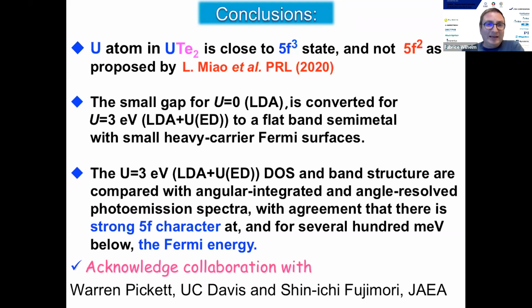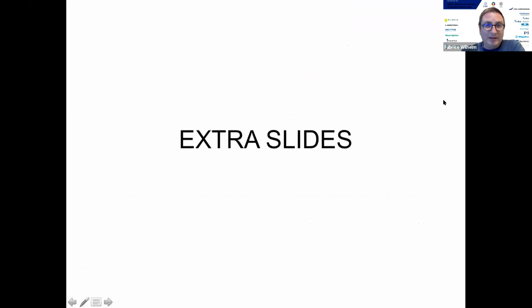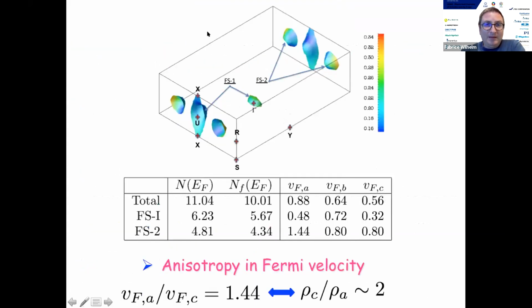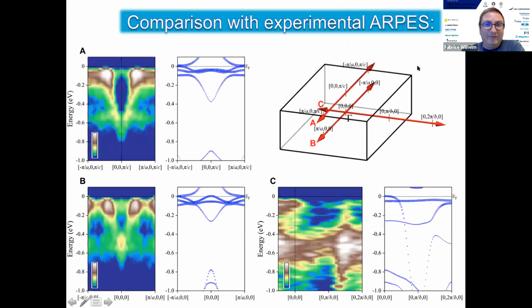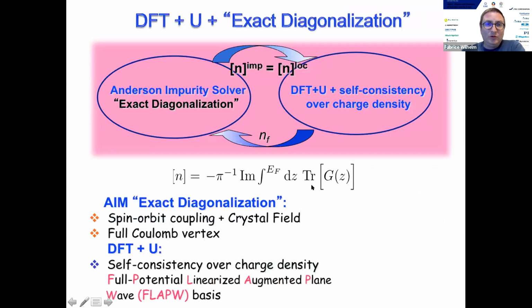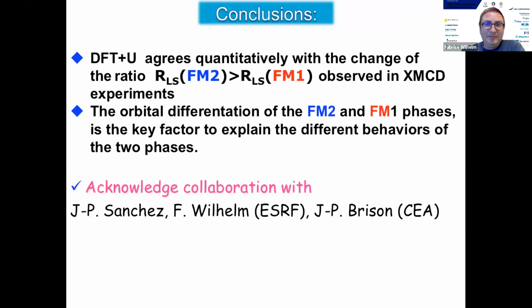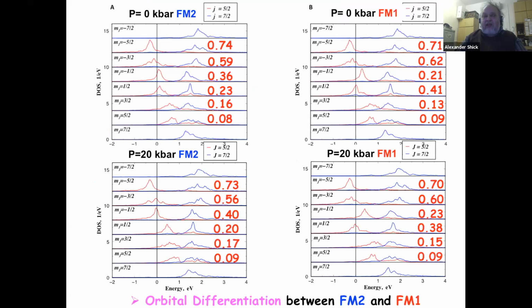I have a question regarding this orbital differentiation, which you talked about for uranium germanium 2. Does it mean that the number of 5f electrons does not evolve as a function of pressure, when you go from this FM2 to the FM1 ferromagnetic state? Is it constant? It is not exactly constant. It is varying a little bit, but somewhere in the hundredths. So there is no noticeable change like you would expect in a metal-insulator transition. Because some people were saying that when you apply pressure, you go from the localized to the itinerant state. That's not what happens. This pressure is still not big enough to induce such an effect.